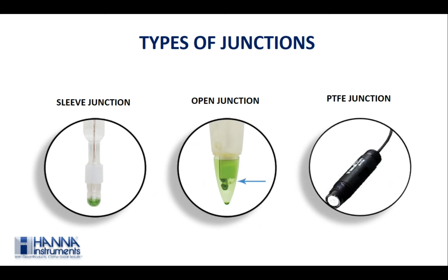This utilizes the porousness of ground glass coupled with a PTFE sleeve to prevent clogging of the junction. The ground glass allows proper flow of liquid while the PTFE sleeve repels the solid. As a result, pH electrodes with CPS technology take up to 20 times longer to be fouled as compared to conventional electrodes. Even if the sleeve junction gets clogged, you can just pull up the sleeve on the upper side of the electrode and clean the clogging. But it is rarely necessary. Cleaning solutions will do the work efficiently.